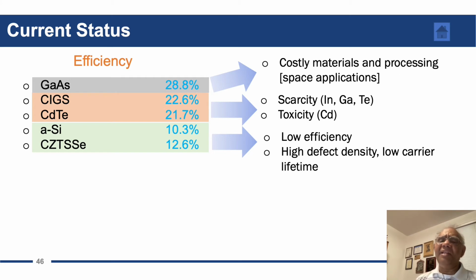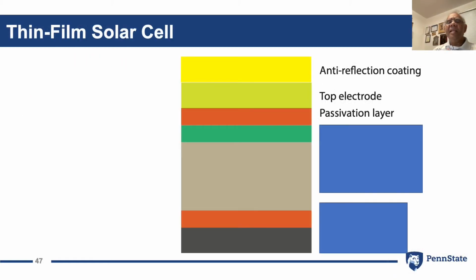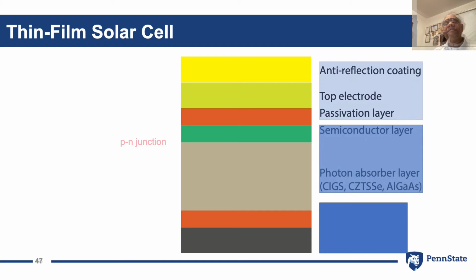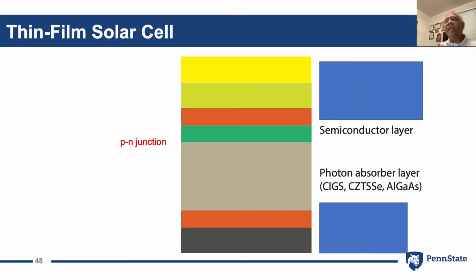Peter Monk and I decided to formulate an optoelectronic model to design such solar cells. This is the typical structure of a thin film solar cell. On top is an anti-reflection coating, then comes a transparent electrode, followed by the top passivation layer. Then come two semiconductor layers forming a p-n junction. The first layer is thin, the second layer is thick.